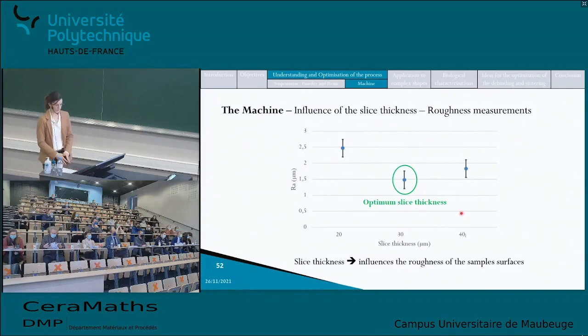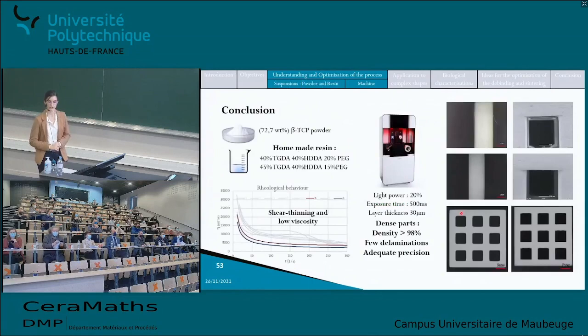So finally, the conclusion of this understanding and first optimization of the process was that it was possible to manufacture a homemade resin with 3 different monomers, the TGDA, the HDDA, and the polyethylene glycol 200. And I was able to obtain a suspension with a shear thinning behavior and a low viscosity. Moreover, using 72.7 weight percent of beta-TCP powder enabled to increase the density of the printed samples and their mechanical properties, and the light parameters, so the light power and the exposure time, were adapted to the composition of the suspension, and also the layer thickness could be adapted to the composition of the suspension.